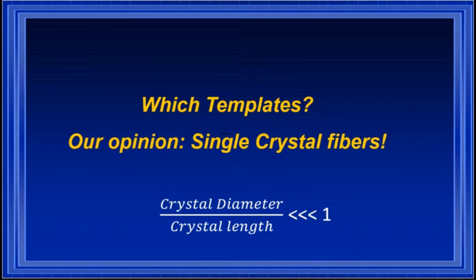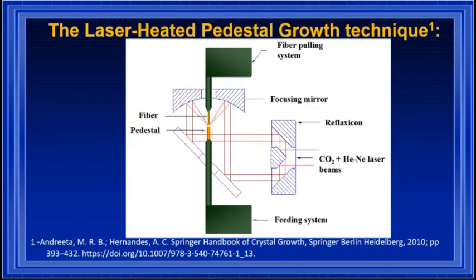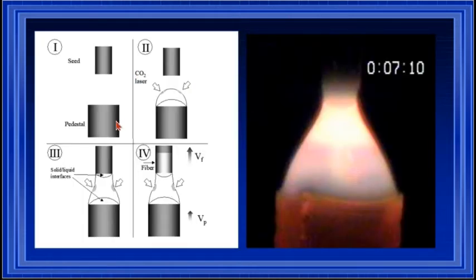And there are some techniques to produce single crystal fibers. One of them is laser heated pedestal growth. In laser heated pedestal growth, a CO2 laser is used to heat a pedestal, we will show how we produce it, and create a molten zone. Then the procedure is similar to a miniature floating zone. As we can see here, it's the same procedure as the conventional, well-known floating zone technique.